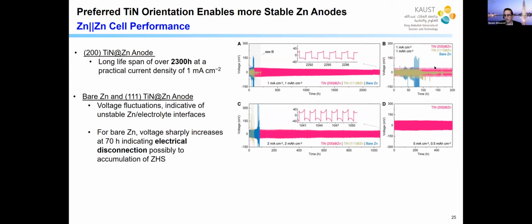You can go to different current densities. Okay, this is 1 milliamp. This is 2 milliamp, and this 5 milliamp, and you will get the same result. So this is substantial improvement by using the titanium nitride with the 200 orientation.